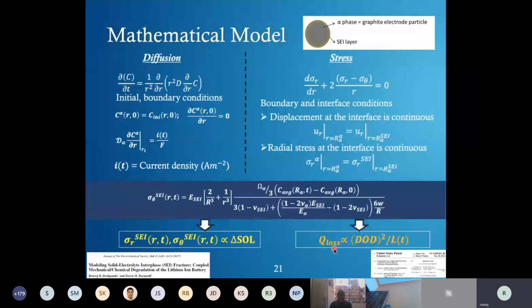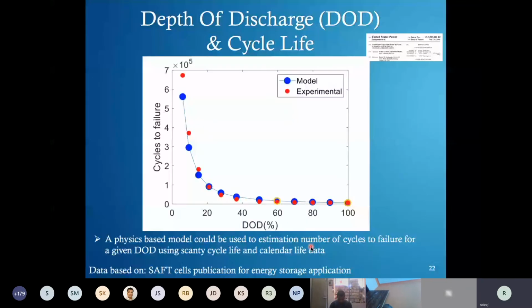It is important because now we can predict how many cycles a cell can do for various depths of discharge, even if we don't have data. Remember, we have scanty, very limited data of charging and discharging, and we still need to understand how our cell will perform in a given situation. For example, in this case, we had only two data points, the red circles. The red circles are the experimental points, and the blue are the model estimation. But we see that until at least 20% depth of discharge, we could predict very accurately, based on a physics-based equation, the number of cycles to failure for a given depth of discharge.